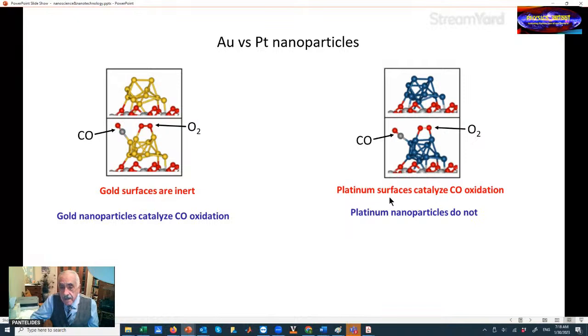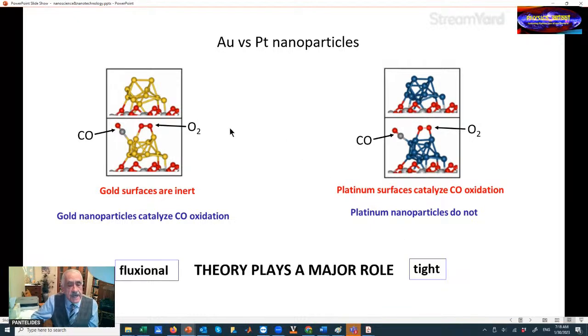Platinum does the opposite thing. Platinum surfaces catalyze CO oxidation, but platinum nanoparticles do not. Again, this is an example from my group, and this is an example to show that theory plays a major role in nanoscale science and technology. We discovered through calculations and simulations that gold nanoparticles are fluxional. That means the gold atoms are not solidly bonded, but they rattle around, move around, and as they move around, they bring the CO and the O2 together and they react.